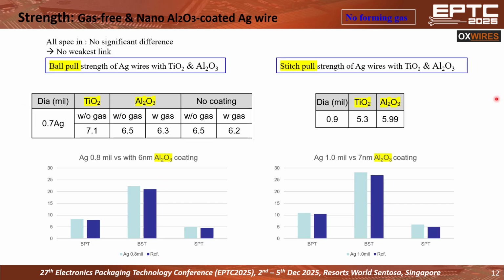And on the next slide, I'm going to show you the strength of ball pull test, ball shear test, stitch pull test. Reference means no coating. With no coating, the ball pull strength is 6.2 gram. In the case of Al2O3, 6.3, 6.5, they are almost the same as the no coating cases or reference. And TiO2 is 7.1 gram, almost the same. And on your right hand side, when you look at the stitch pull strength, the reference here is no coating cases, and the ball shear and stitch pull strength don't change much at all by introduction of TiO2 passivation and Al2O3 passivation. Again, I'm going to have to emphasize that no forming gas was used.